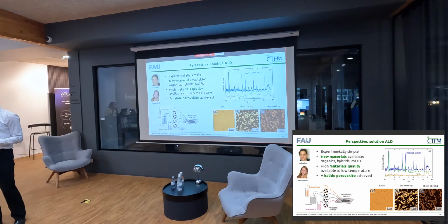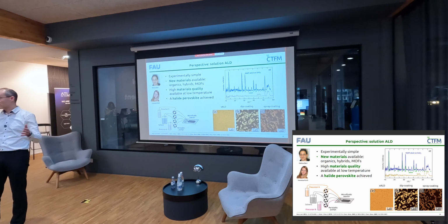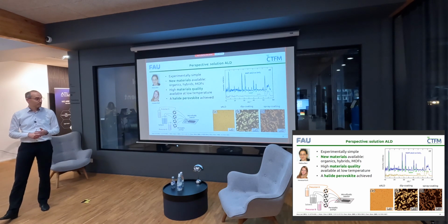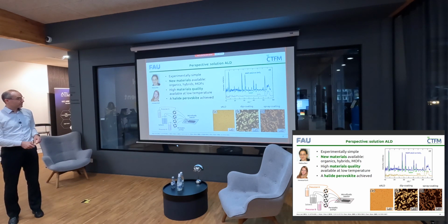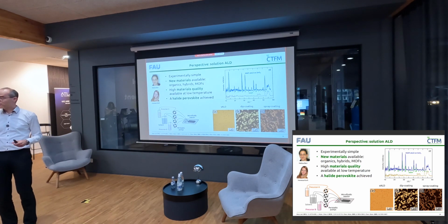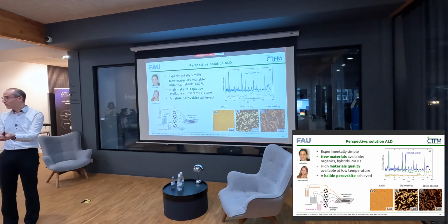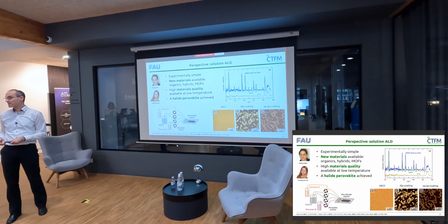And for all those, I think we have a solution, literally. It's performing ALD from the solution phase instead of from the gas phase, because those are all precursors that you can actually bring into a liquid phase, that dissolve in solvents, organic solvents, water, you name it, even perhaps one day supercritical CO2. For example, we've deposited metal organic frameworks, MOFs. MOFs are a class of porous materials that actually need a solvent because that is the molecule that uses the space that generates the pores. Without the solvent, you don't get crystalline MOFs.